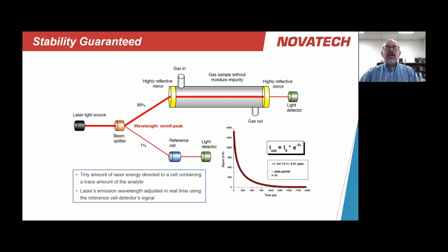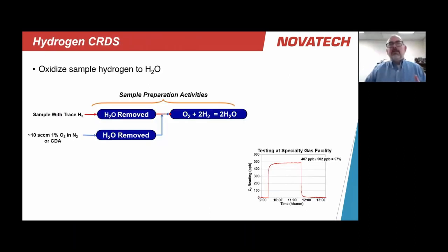We measure hydrogen in an interesting way. With these analyzers, we actually don't measure the hydrogen directly, unlike the tunable diode laser analyzer that we saw earlier. In this case, we actually dry the sample, remove any traces of moisture from it, and then combine it with oxygen from air to form moisture so that we have a known concentration of moisture to hydrogen. It's a 1-to-1 ratio, basically. And then we measure the moisture. We have very high sensitivity for the moisture measurement. The wavelengths of interest are very powerful. We have good signal at those wavelengths.